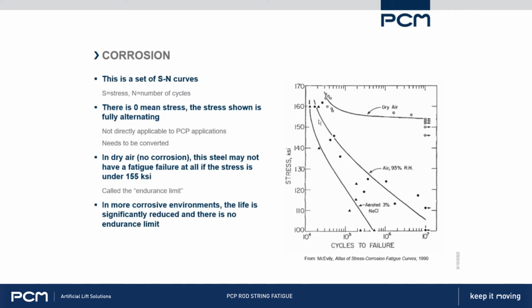The second line is just in moist air with 93% humidity. So you're in a tropical climate or something like that. And here you can see there's a much steeper curve. We do have a couple of points here that have got to 10 million cycles. If you're below about 112 KSI, it hasn't failed yet, but with the presence of corrosion, that doesn't mean it's going to last forever. It just hasn't failed in 10 million cycles.